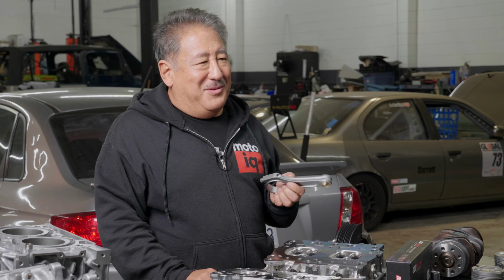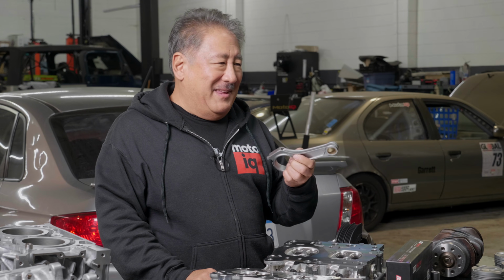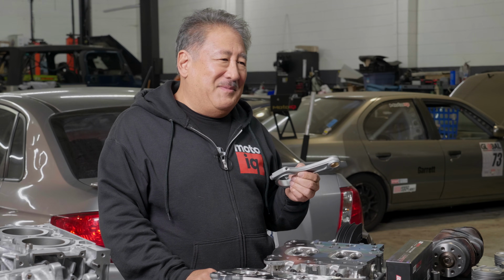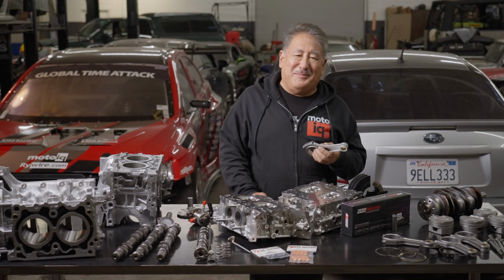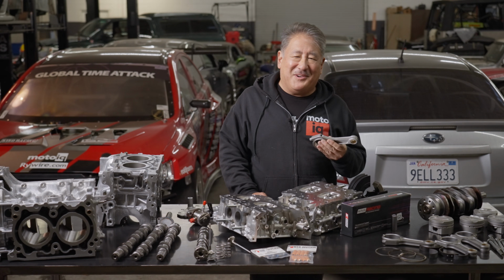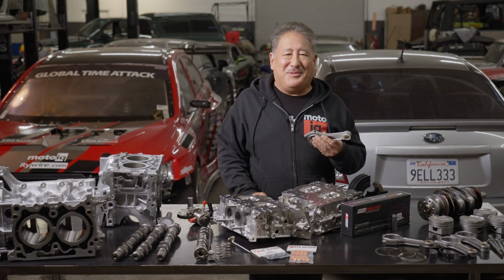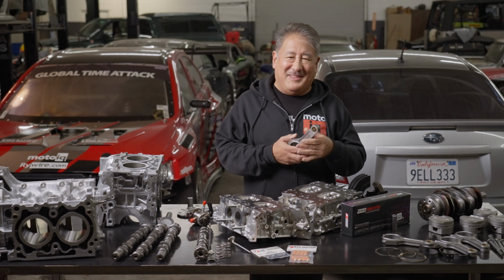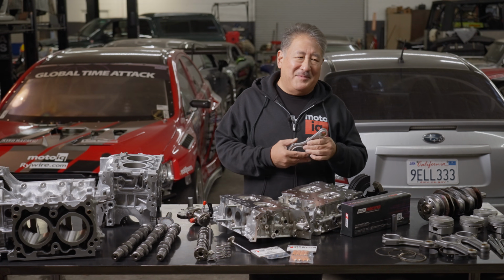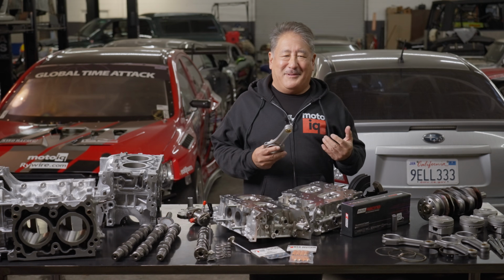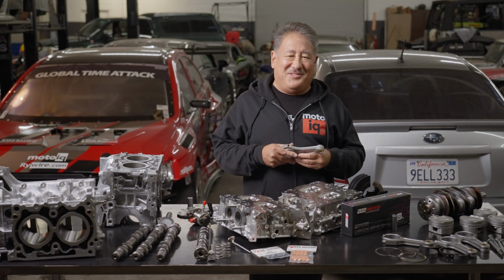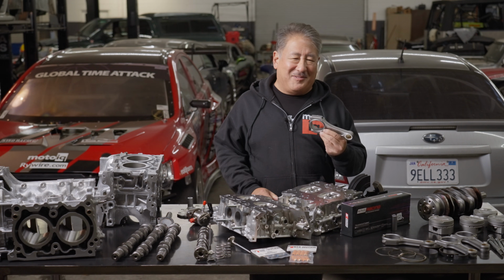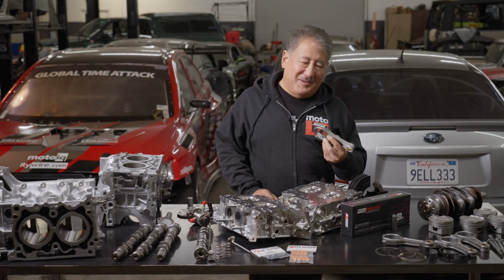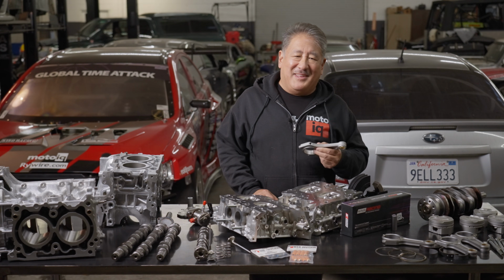On the FA motors, the connecting rods are probably their Achilles heel. When you're tuning them, if you run above 330 foot-pounds of torque, and for sure if you run above 350 foot-pounds of torque, you tend to bend the rod. This usually isn't a catastrophic failure, and if you catch it, you could usually save the engine, but bending the rod isn't cool. So it's really important to get good rods in these motors.